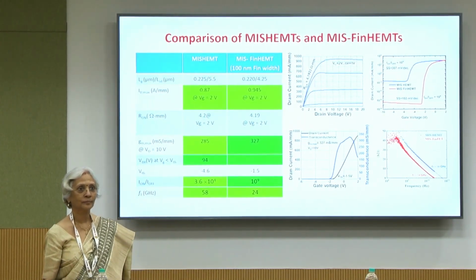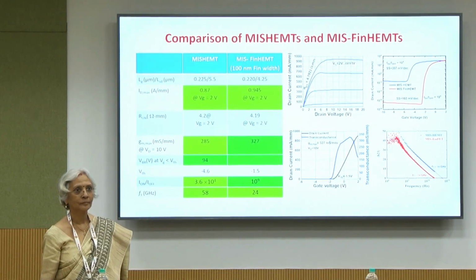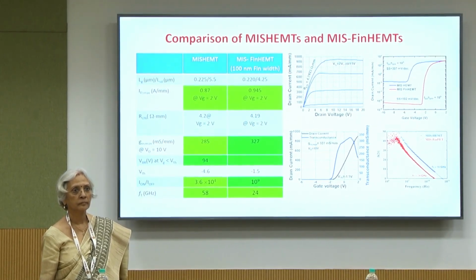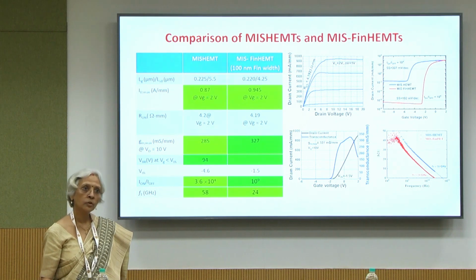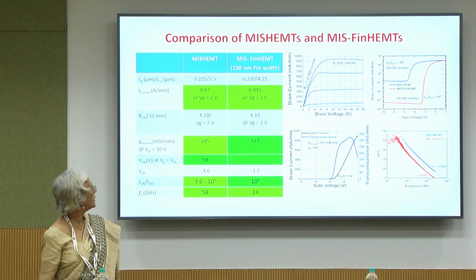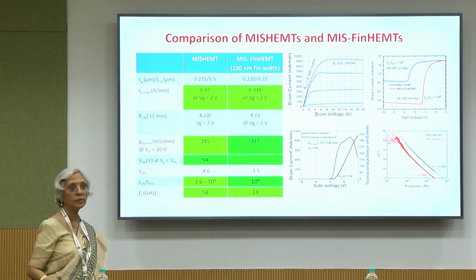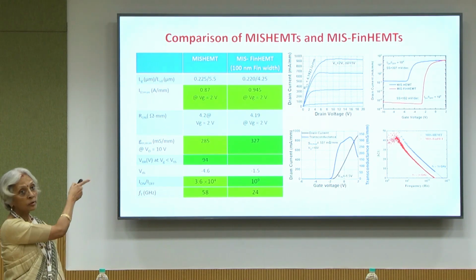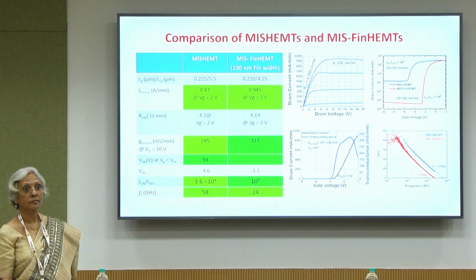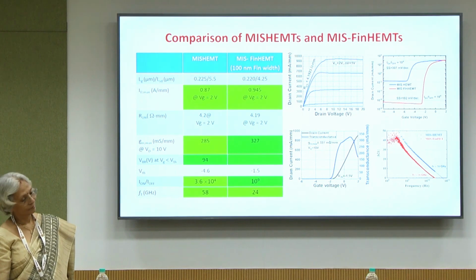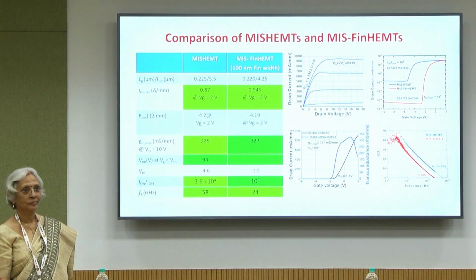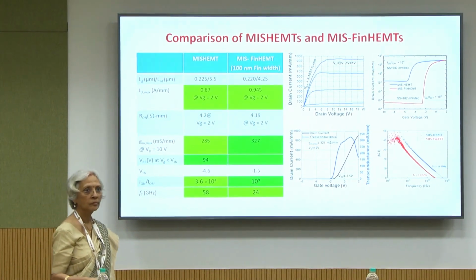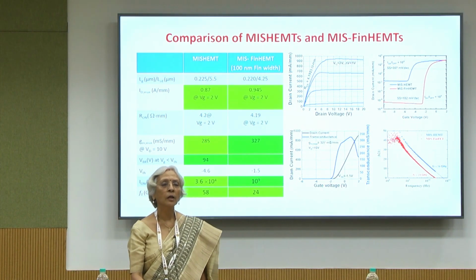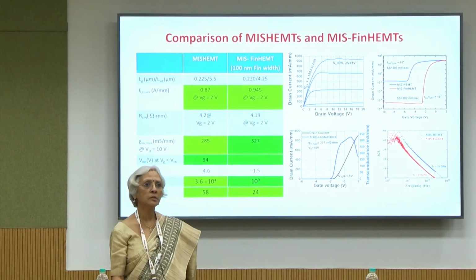On state when you have high V into I dissipation, so is the dissipation a function of the fin width, like self-heating effects? In FinFET, the self-heating effect is much less, as you can see from this plot. Look at this plot, the self-heating effect is actually much less. But in MISHEMT it would be more prominent. So, what would explain that difference in self-heating effects between a FinFET and a non-fin structure? I think it's because the heat gets dissipated easily for the FinFET.